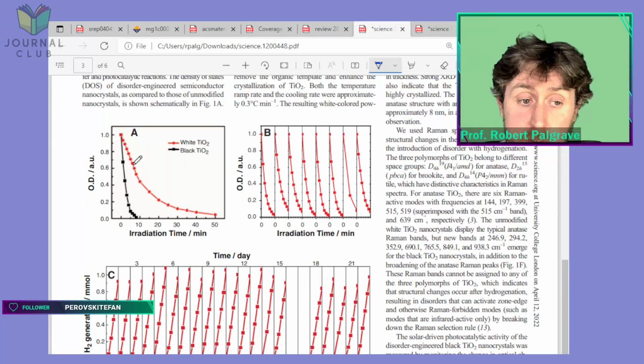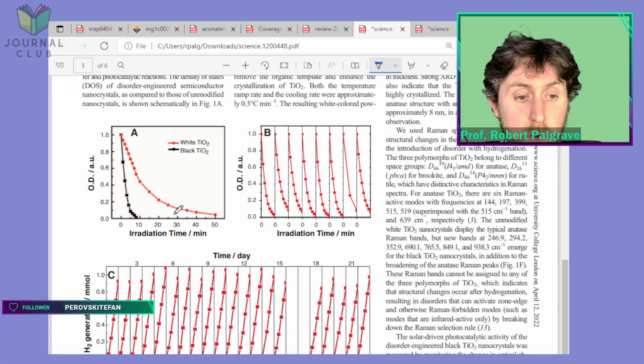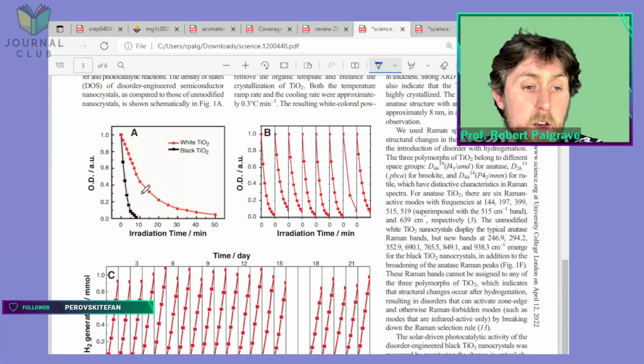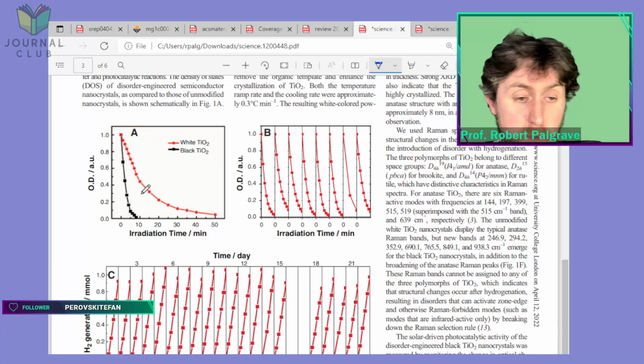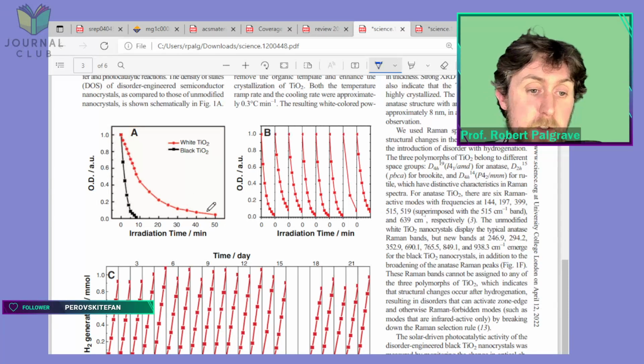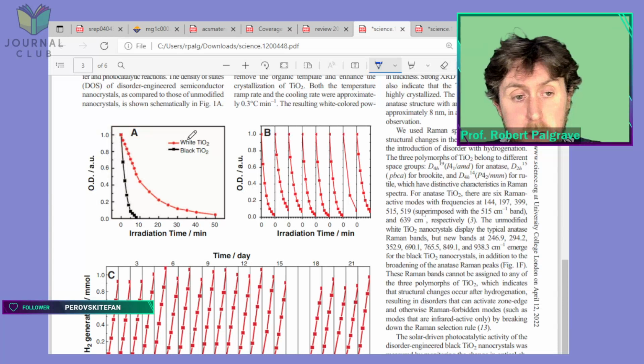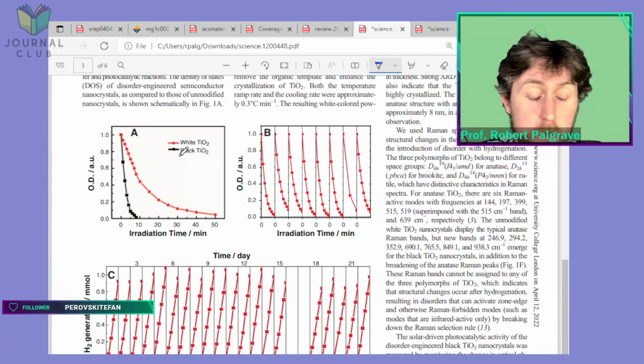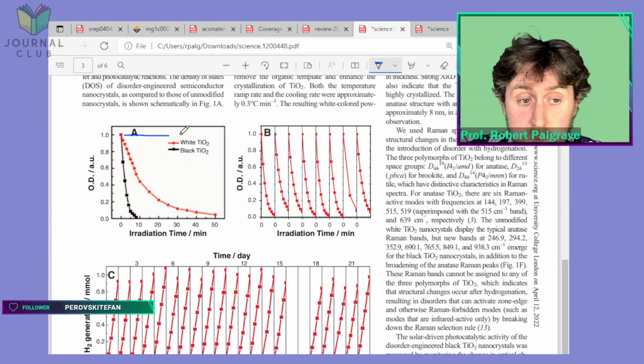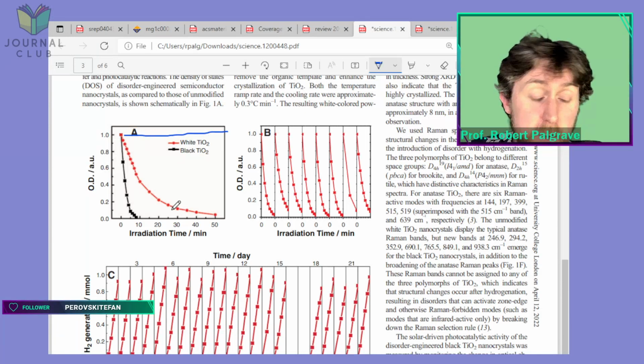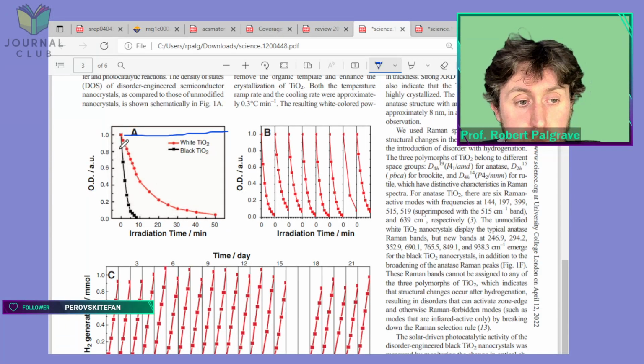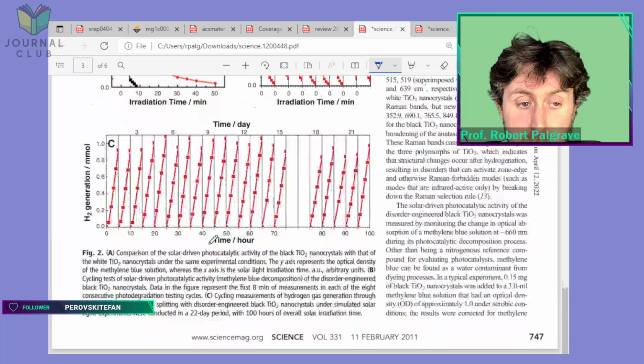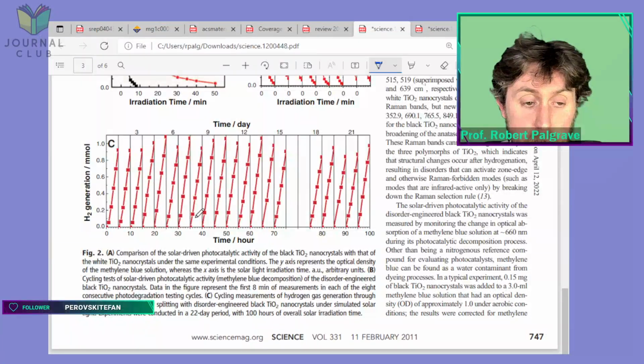Note, white TiO2 is still doing something, so I think what that tells us is that the light they're irradiating this experiment with when they're doing the photocatalysis must have some UV component, otherwise the white TiO2, the undoped TiO2, would do nothing at all. You would just expect to see a straight line across the top. But the fact it goes down means there must be some UV there, but it's clear that the black TiO2 is doing a better job, and they didn't just do this once, they repeated it many times, and you can see that they also generated hydrogen using the same method.